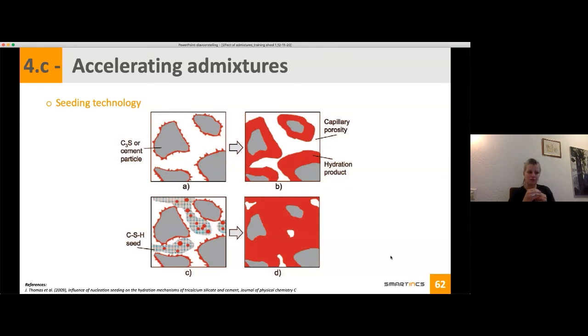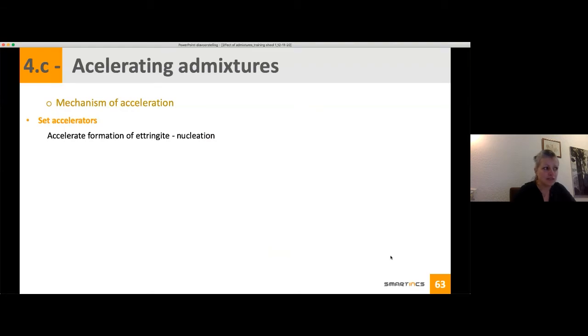Now, what happens with what they call seeding technology? You have your cement particle and your hydration product the same way. But where you have your seeds, and you can have a CSH seed, they act as nucleation points, which means that your hydration products can grow over much more area inside your system, and so your microstructure will develop faster. This is a really nice technology, but it's also relatively expensive compared to the other accelerating admixtures. So for specific applications it's an added value, but it's not something you will use for all applications.